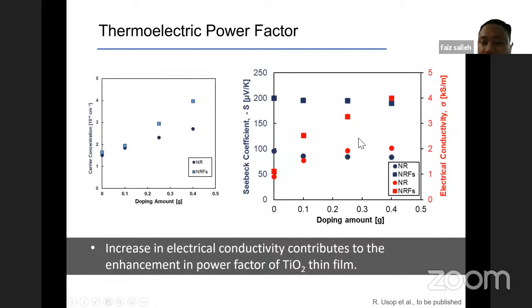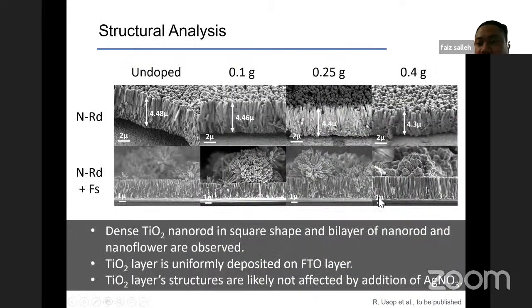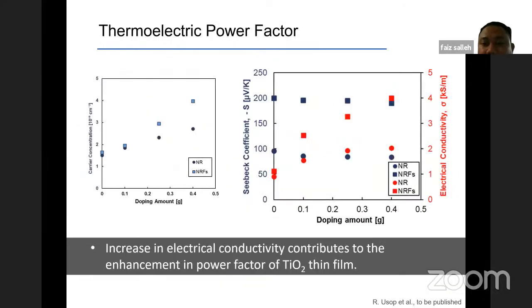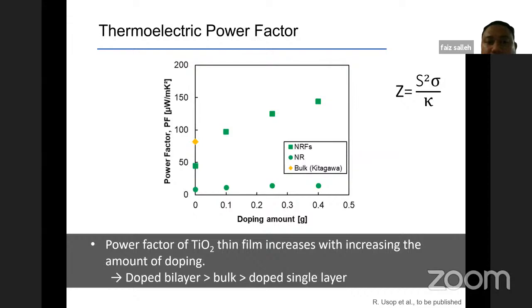So we can see here that the increase in the power factor is mainly governed by the electrical conductivity, and the improvement of the electrical conductivity is due to the increase in the carrier concentration by the oxygen vacancy when we dope with silver. So we can consider the increase in electrical conductivity contributes to the enhancement in the power factor of the TiO2 thin film with doping as low as 0.4 gram of silver nitrate inside the process. And we can see that the structure is also not much influenced by the doping, so we can keep the benefit of the nanostructure. Simultaneously, we can also increase the thermoelectric power factor by increasing the carrier concentration.